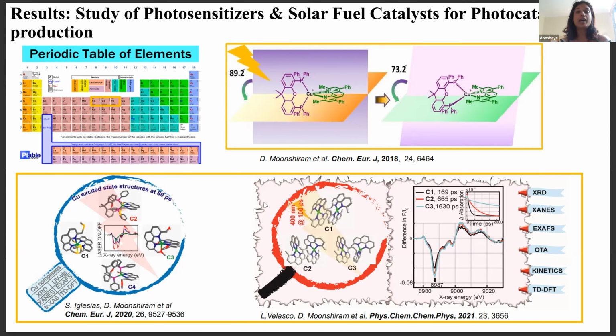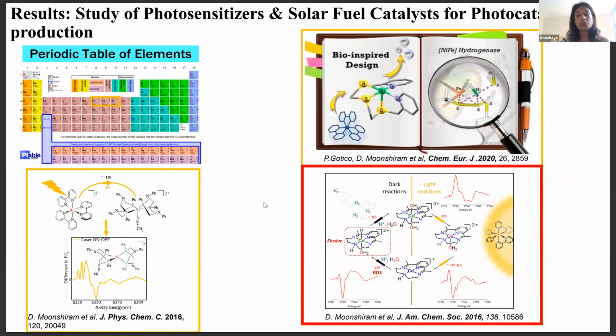And our results allowed us to determine more rational ways to improve the stabilities and the lifetime of these complexes, for incorporation of more rigid and bulkier ligand supports. We also coupled these photosensitizers, both earth-abundant ones as well as the typical ruthenium bipyridine photosensitizers, with earth-abundant nickel, cobalt, and iron complexes. And by combining ab initio theoretical simulations with pico- to microsecond X-ray absorption techniques, we were able to determine the reaction pathways, but also assign a complete mechanistic pathway followed by these catalysts in the pico- to microsecond timescales.